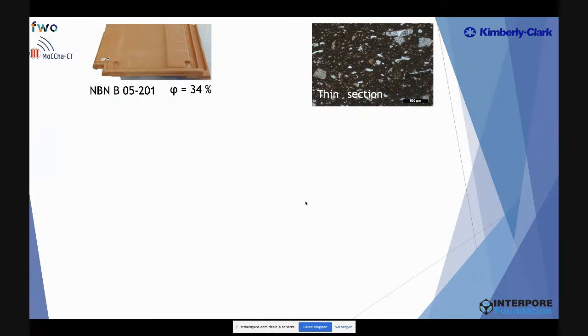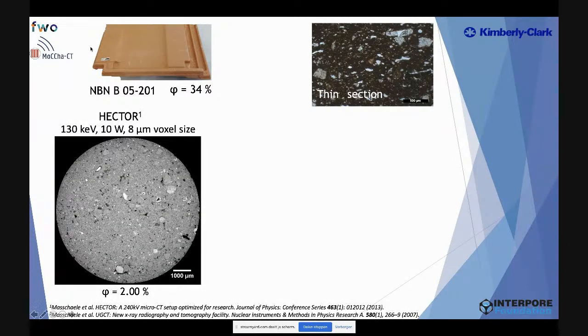So we did an experiment on a roofing tile, which is a difficult one to image with normal absorption CT, because we know it has a high porosity, 34% in this case, but we know that most of the pores are below 1 micron. If we scan a piece of this tile with normal absorption CT at a voxel size of 8 micron, we see immediately that we only get around 2% of porosity visible.